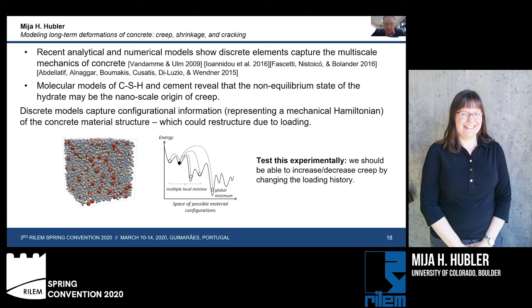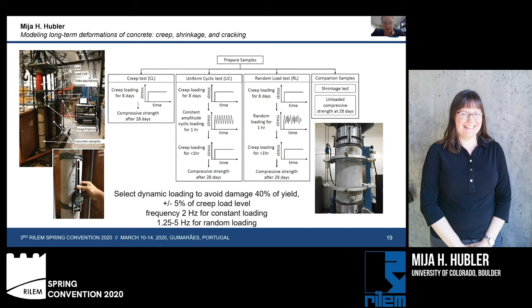So if these molecular numerical models are correct, we should be able to test this on the macro scale experimentally. That means I can increase or decrease the creep if I put energy into my system. The easiest way to put energy into a system using the experimental techniques available to me would be to load the system. So this is what we've done. We've developed a testing protocol here where we prepare a number of concrete samples, first of all, and then have these parallel tracks to our experimental campaign.